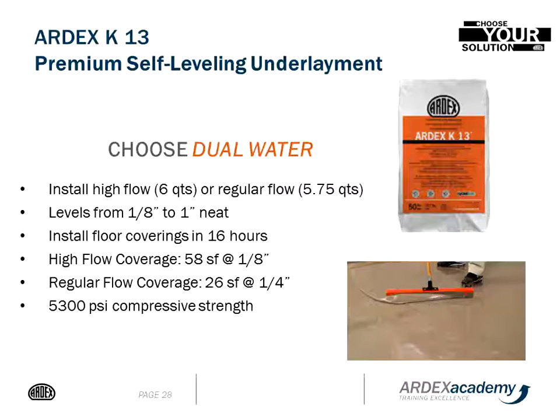The regular flow coverage at 1/4 of an inch is 26 square feet per bag. The high flow, which some of you may be thinking, well, if I'm going from 1/4 to 1/8, it should be about 52 square feet if we're doing 26 at 1/4. But with the high flow, a little bit extra water, your coverage increases as well. So you're at about 58 square feet at an 1/8 inch.